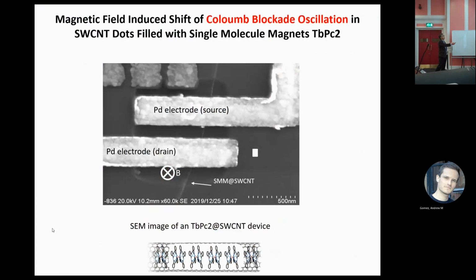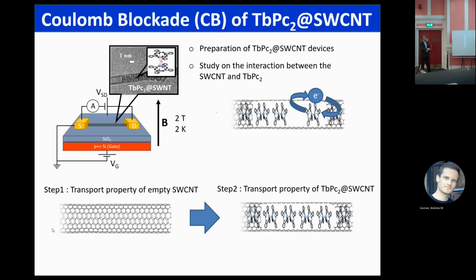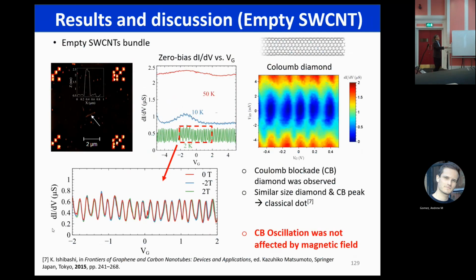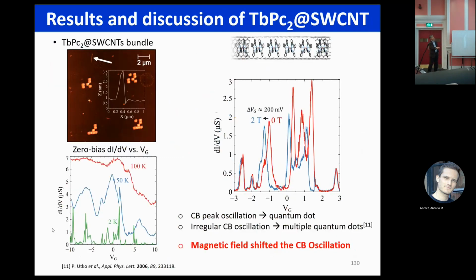So this is a carbon nanotube. This is a palladium electrode. We get this device by lithography. So then before encapsulation and after encapsulation, we compare the Coulomb blockade. Before encapsulation, very beautiful oscillation observed. And we switch the external field. The single carbon nanotube doesn't change because there is no spin before encapsulation. But after encapsulation, it is very noisy because the conduction electron and localized spin interact, and spin flip occurs.